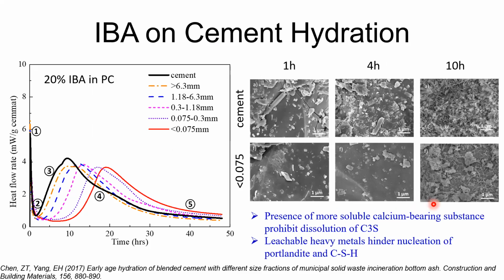In a separate study, when we try to study the influence of using IBA in cement, we replace 20% of the Portland cement using IBA with different size fractions. It's very clear to see that using smaller fractions of IBA has a very clear retarding effect.